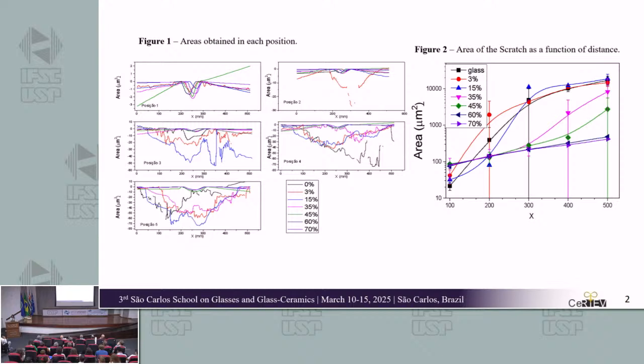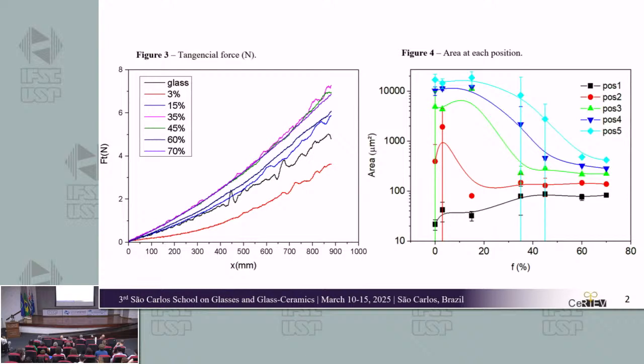The scratch area, tangential force measurements, and the measured areas and the maximum depth obtained at fixed positions along the scratch were analyzed. The measured scratch areas were evaluated as a function of the crystalline fraction and the load applied at 5 positions along the scratches. More details will be provided on the poster of the work shortly. Thank you.